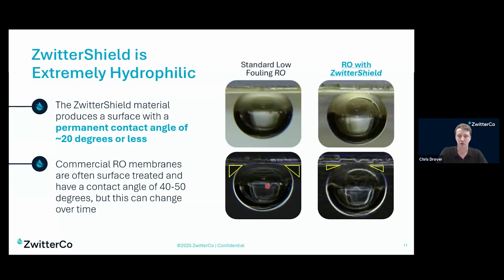And so down below, you can see we've got some contrast enhanced images. We're calling out that angle. But if you focus your attention above, you'll notice on the left, this air bubble, the air is kind of grabbing a lot of real estate here, right at the interface. The air membrane contact area is fairly large, and it's pushed the water out to the sides, and that's why it's forming this kind of steep angle at the edge of the bubble.